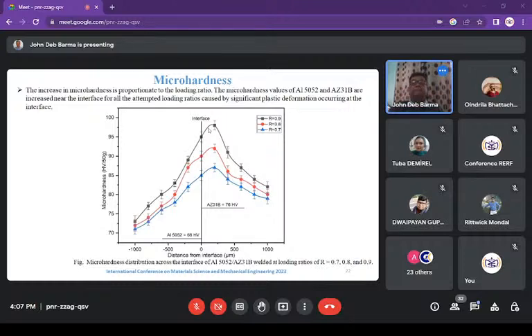And also the micro hardness value of this aluminum 5052 and AZ31B are increased more at the interface, as you can see, for all the attempted loading ratios. Here it is at the interface. These are significantly more in comparison to these values. And so you can say that this is more because this is caused by a significant plastic deformation which took place at the interface.